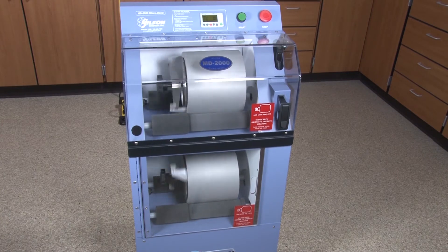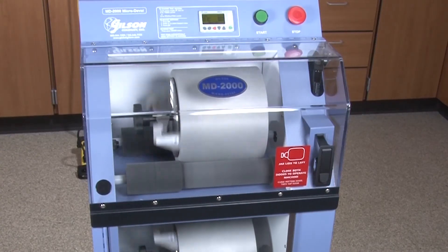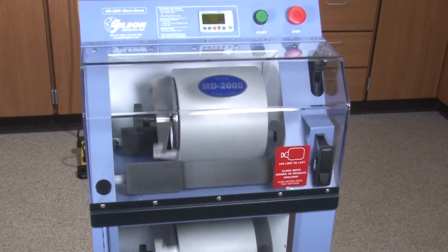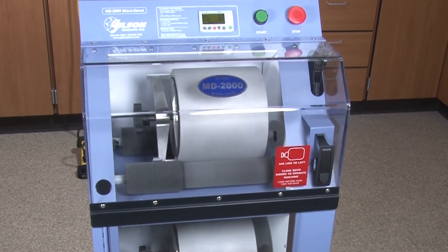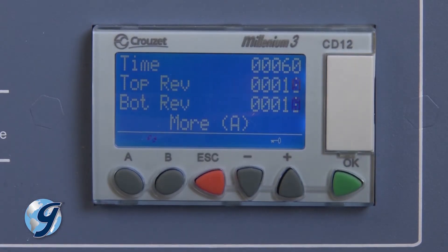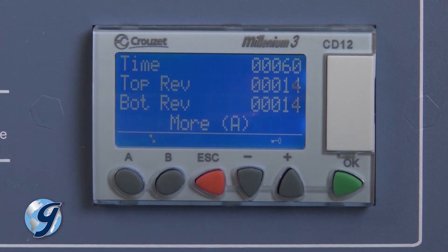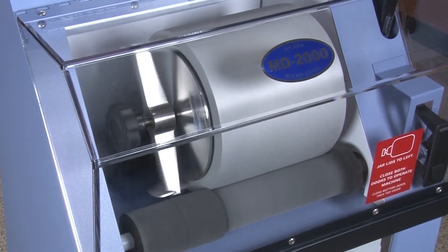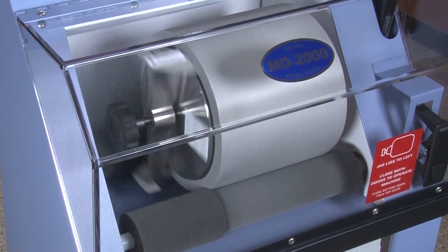The sample and charge are considerably smaller than those used in the LA Abrasion Test method and are not subject to significant impact forces. Test results are more focused on durability and hardness and to predict the aggregate's abrasion resistance.